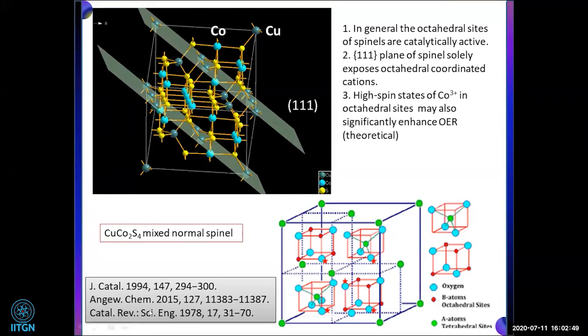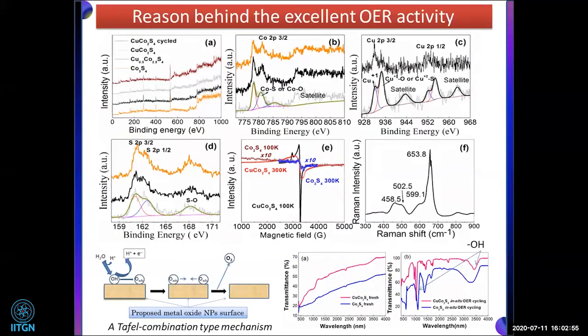These are the theoretical results, they have explained this, and that's what we got: a very nice oxygen evolution from this copper cobalt sulfide nanosheets. One more thing I want to say: originally the material is cobalt sulfide, Co3S4. So we introduced copper here. Because of the introduction of the copper, it pushes most of the cobalt ion, Co2+, to the 3+ ions.